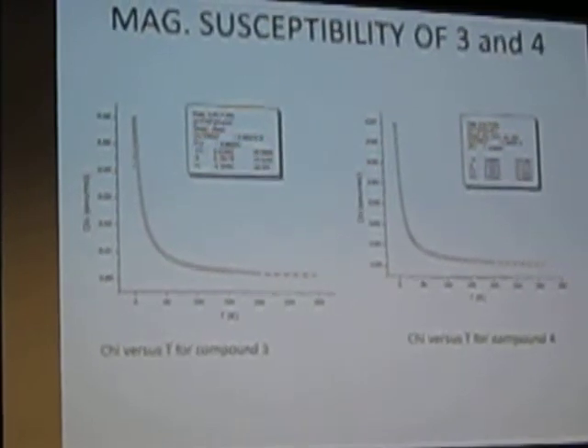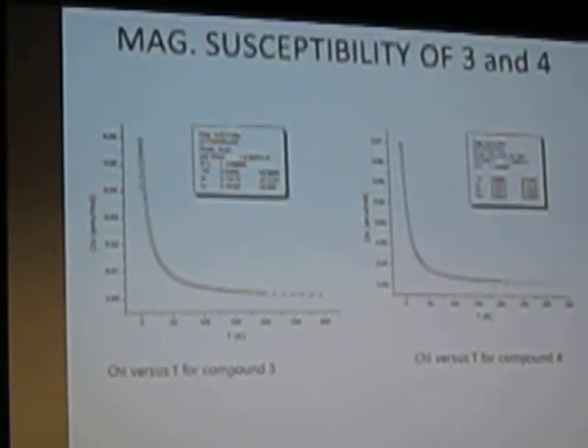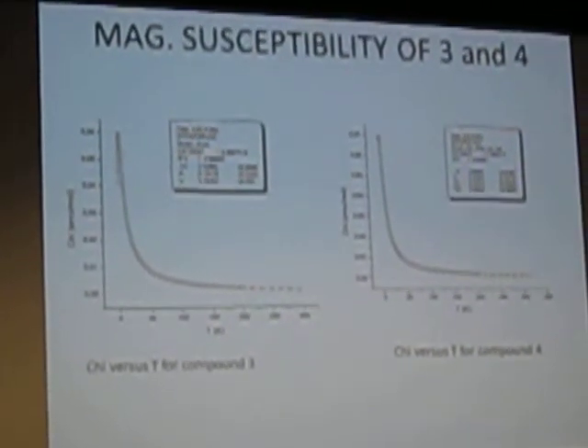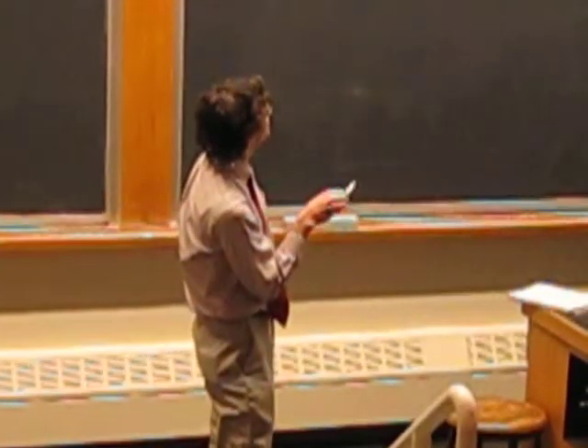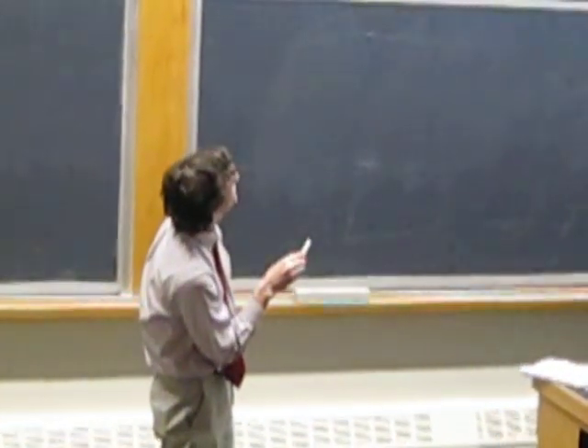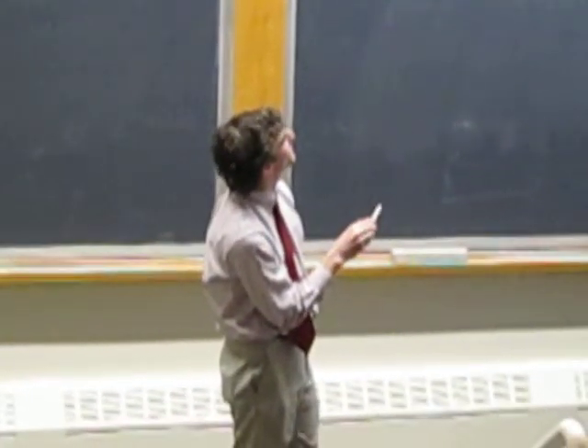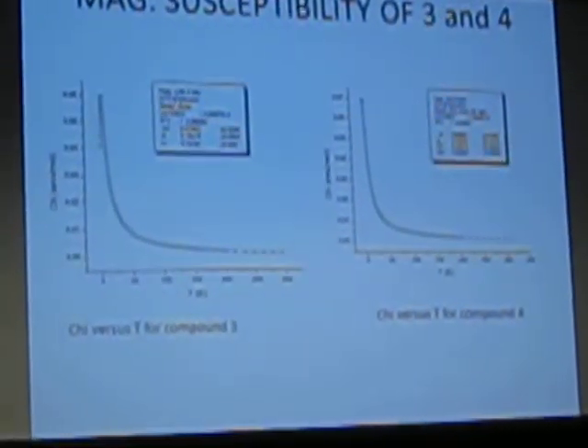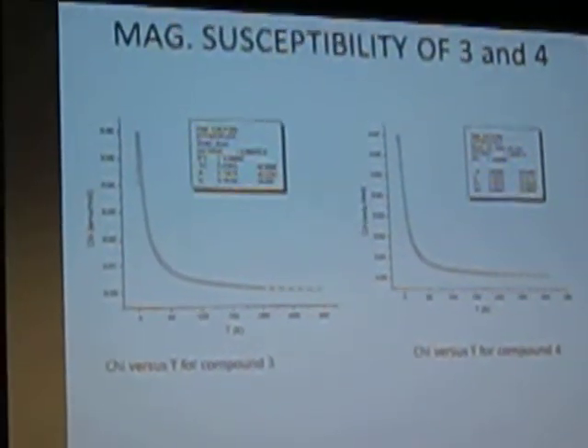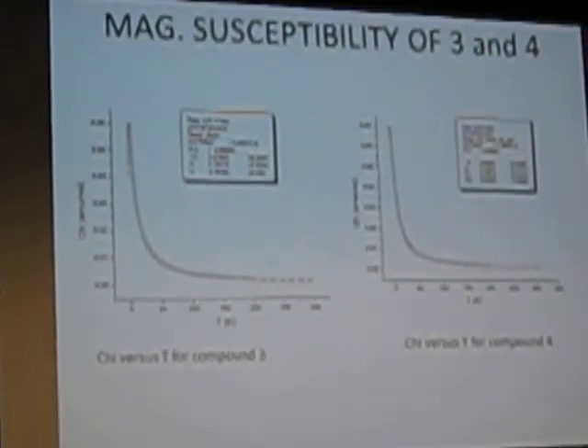Now we don't have any structural data on compound 4. The crystals are just not single, so that's a problem. So we're going to need to see if we can grow single crystals of this material to actually get some structural data. We cannot deduce anything from the magnetic susceptibility data. There's only a very small hump here for the turnover in chi versus T. So there's no real structural characteristics that we can deduce from this sort of plot. So we're really going to need some structural data to see what's actually going on in those compounds.